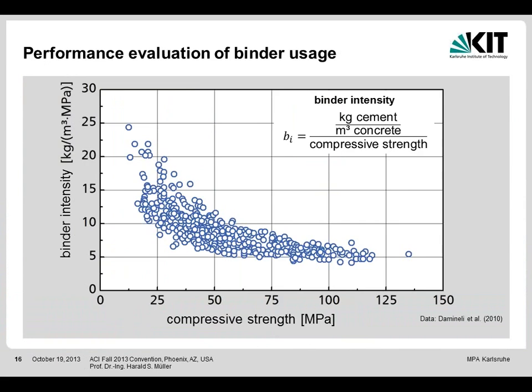If we do this for traditional concrete compositions, we find points like plotted here, and you see the higher the compressive stress we realize, the lower is the cement content used to gain this high strength. This means there is much room for improvement for low strength concrete, and much lower room or no more room for high strength concrete. It's better, and also Professor Sakai mentioned it, to produce high strength concrete. It's very clear from this relation.